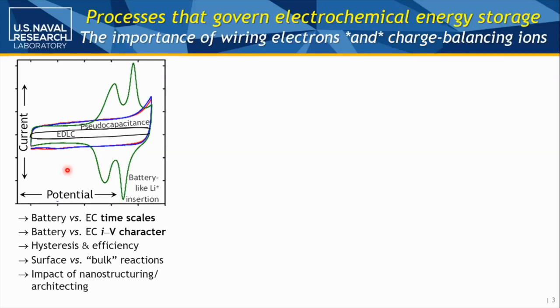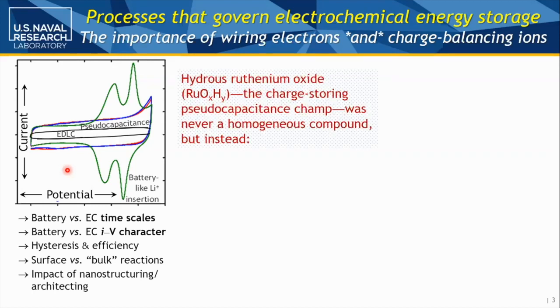What is surface if you've got a porous system versus a monolith, something that's tens of microns, that the electrons and ions have to get into and out of? And what happens if you think in terms of nanostructuring or architectural design? And we backed into this because we were trying to understand the pseudocapacitive champ, hydrous ruthenium oxide. And the fun thing about that material, RuO2, is rutile crystalline, electronic conductivity approaching that of copper, not a very good pseudocapacitor. But if you start to put hydrous character into it, you can really store charge.